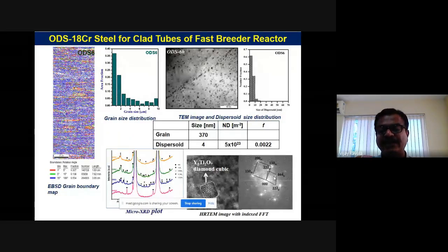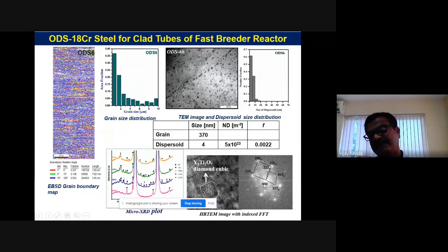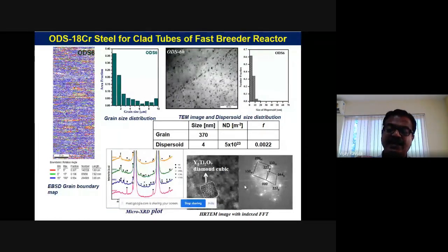And even if you look at the 18 chrome, typically this is an EBSD grain boundary map, and you can see the grain size distribution. So the grain size is around 370 nanometers, and the dispersoid size, the oxide size, is around 4 nanometers. And if you look at the typical particles, what is the structure of the particles, you could see that this is Y2Ti2O7, and this is a selected area diffraction image. And then we can always see that the KS relationship is maintained, and there is an orientation between the matrix and the particles.